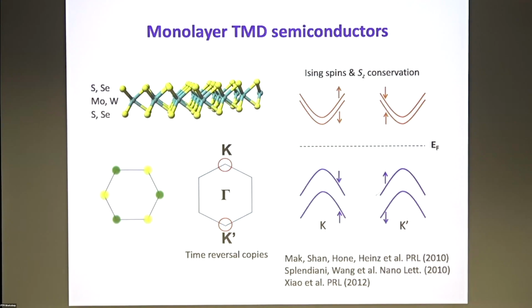So this is the band structure taking into account the spin-orbit interaction. You can actually see that there's a huge spin splitting at the K and the K prime points. The splitting is opposite, so that it preserves the time reversal symmetry. So you can think that basically the electrons at the K point or the K prime point break time reversal symmetry, but they just break it oppositely so that the entire system has time reversal symmetry.